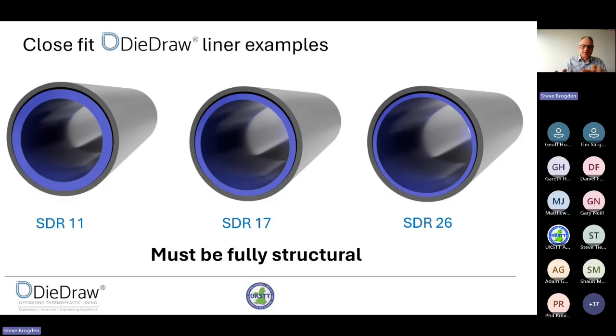Now, these are what I call close fit liners, where in the water industry, most frequently we will have a close fit liner rather than the tight fit liner. The reason for this is we will be using a specified polyethylene pipe size. For example, we might be putting a 280 pipe in a 300 or a 315 pipe in a 300. If you put in a 315 pipe, you get a tight fit; if you put in a 280, you're going to get a close fit instead.